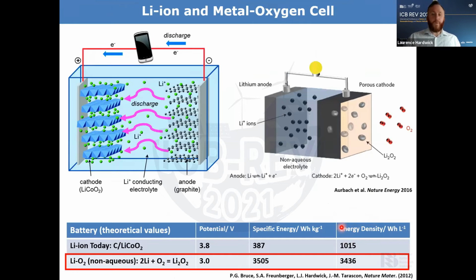So what I'm going to talk about today is our metal oxygen cells. Here we have the lithium-ion cell, where you have your positive electrode of lithium cobalt oxide and negative electrode of graphite, and lithium ions shuttle between the two through intercalation reactions. The metal air cell works slightly differently. You have, in this example, a lithium metal electrode, where you strip and plate lithium. And as you strip the lithium ions, you can reduce oxygen on a porous electrode and combine electrons, which are doing useful work, to grow lithium peroxide within your cell.